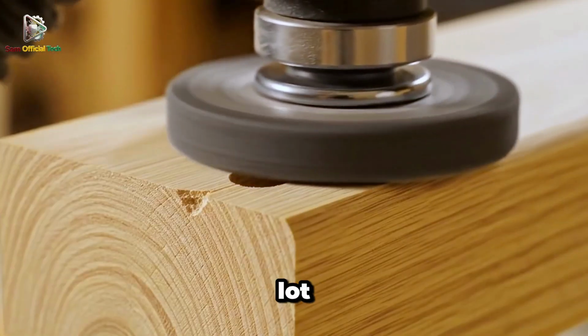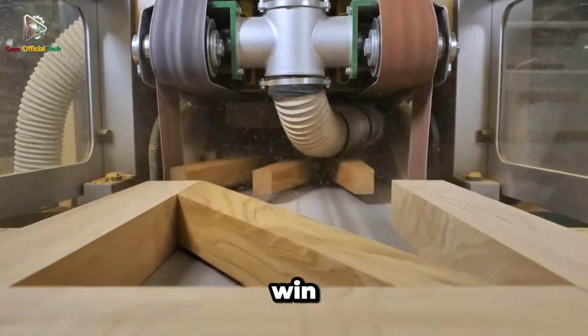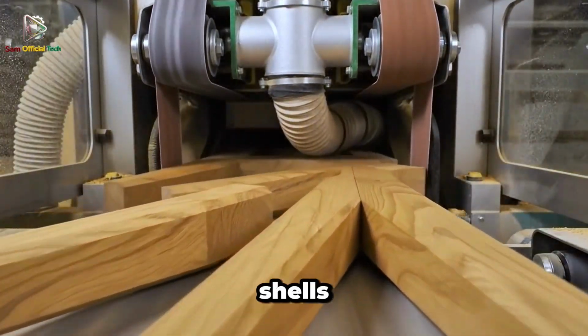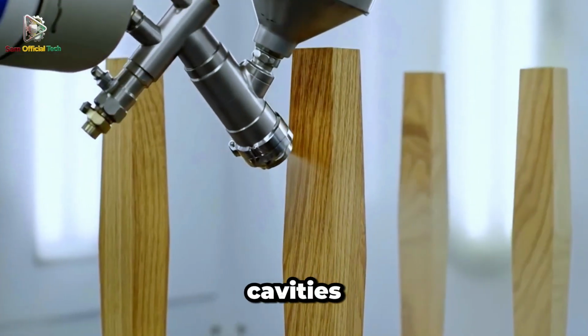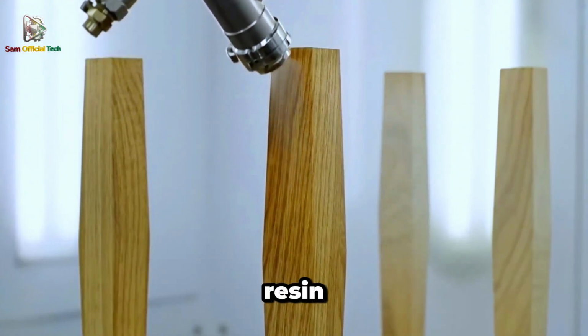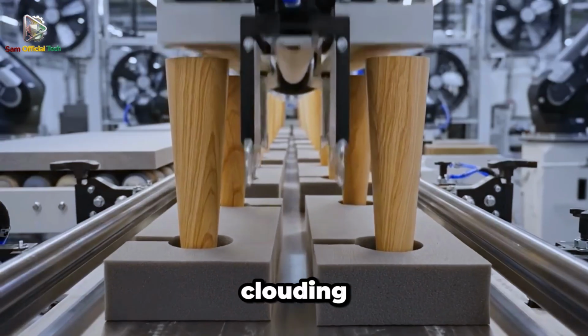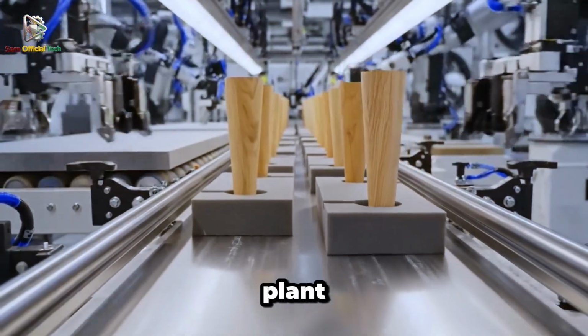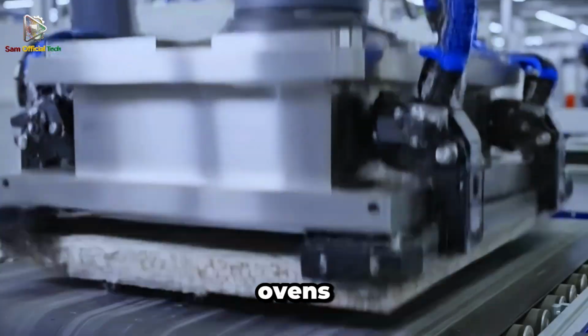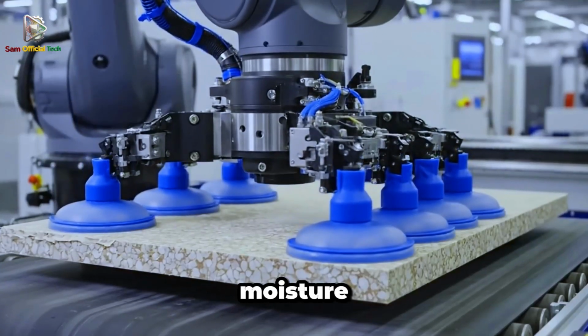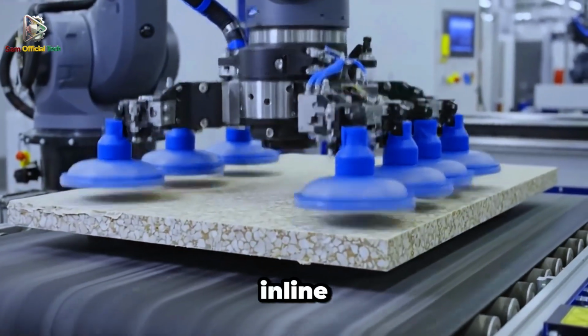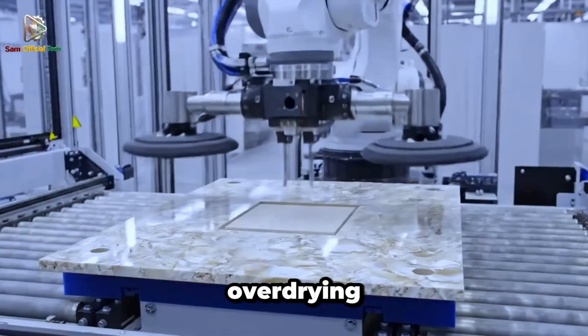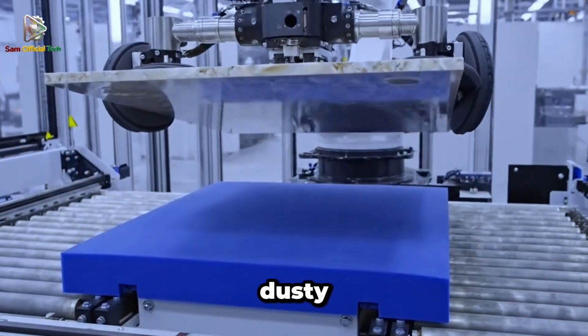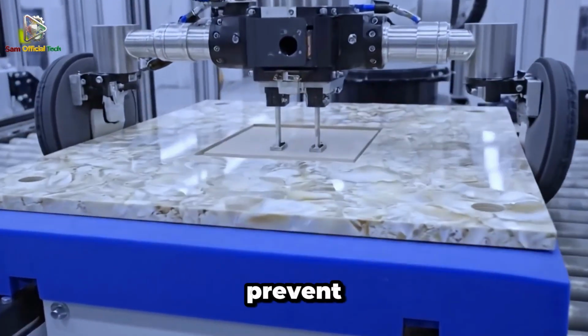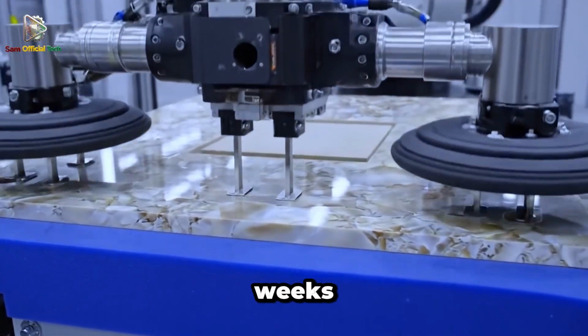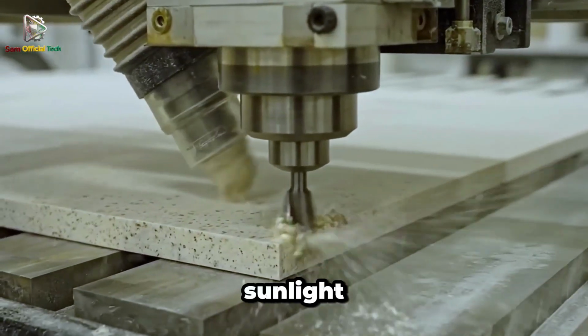Drying is where a lot of shell table factories quietly win or lose quality. Shells hold moisture in microcavities, and moisture trapped under resin causes bubbles, clouding, and delamination. So the plant runs belt dryers or batch ovens with controlled airflow until moisture hits a narrow target. Inline moisture checks prevent over-drying that turns shells dusty and fragile, and prevent under-drying that becomes a defect weeks later when the table warms under sunlight.